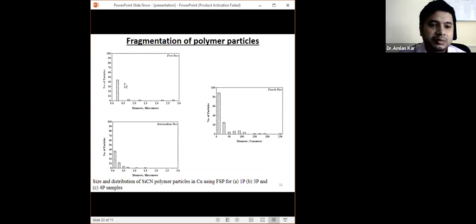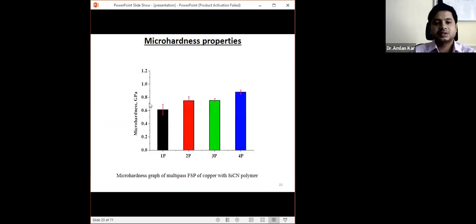And if you see the number of particles after the first pass, the intermediate pass, and the fourth pass, you can see that after the fourth pass there is an increase in the number of very fine particles. This is because of the continuous fragmentation of the polymer particle, which, as I discussed, has low fracture toughness. Because of the low fracture toughness, it gets fragmented, and the coarse particles are reduced to nano-sized particles. The nano-sized polymer particles are consolidated and distributed in the metal matrix. And you can see that with these polymer particles there is an improvement in the microhardness, a little bit, not substantially.